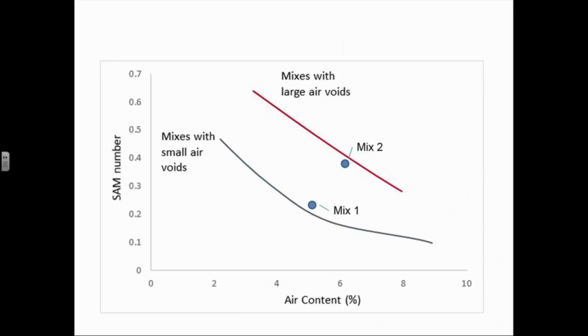Because if I plot those two data points on this line, mix number one, everything was great. Mix number one, I had small bubbles, and they saw it for themselves. They saw that their air void systems weren't stable anymore. Okay? They were plotting near the second line. Also, the SAM number was pretty high. Okay, really high. And it wouldn't necessarily be freeze-thaw durable. It would immediately help them go back and troubleshoot what was going on, what was happening. And this immediate feedback is exactly what our industry needs. Okay? This is simple and easy and fast. And in 5 to 10 minutes, you get this information from your concrete in the field and you can make real-time adjustments. This is helpful.